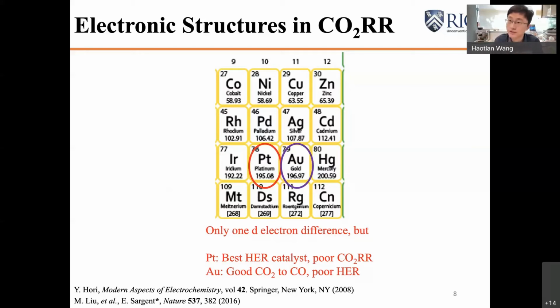But for gold, its neighboring element is nowadays the state of the art CO2 reduction to CO catalyst. So the slight change of the electronic properties actually results in a huge change in their catalytic performance. But if we move our attention away from these noble metals, to these low-cost transition metals, like iron,